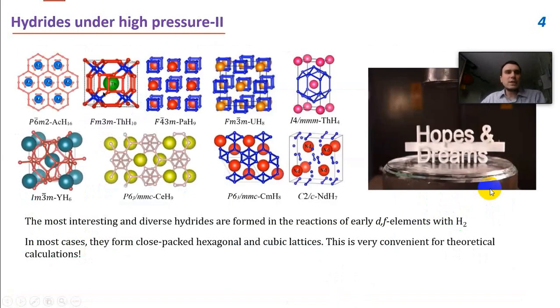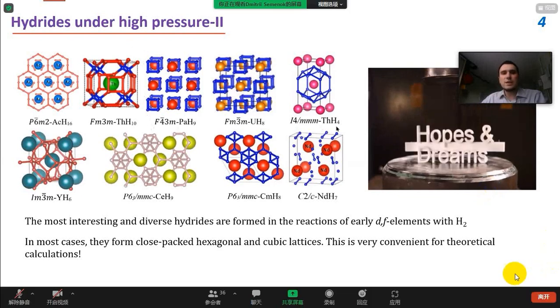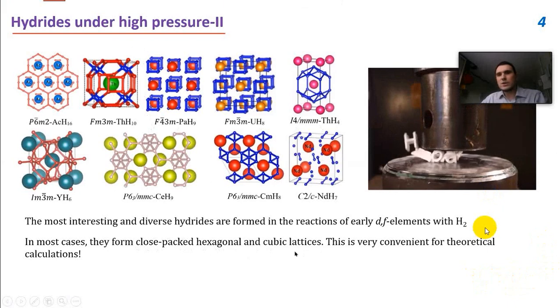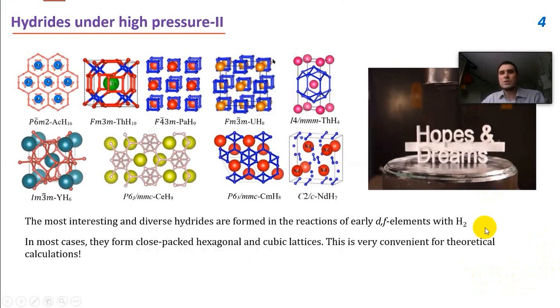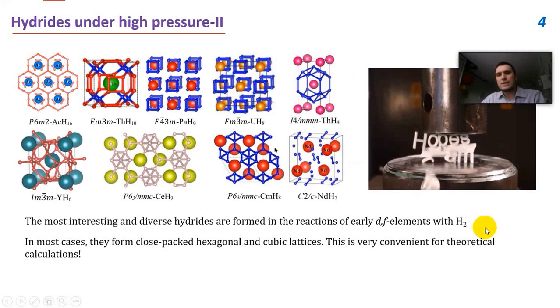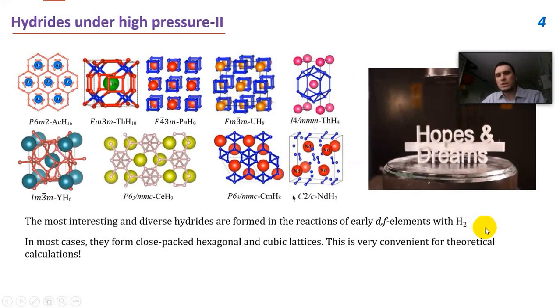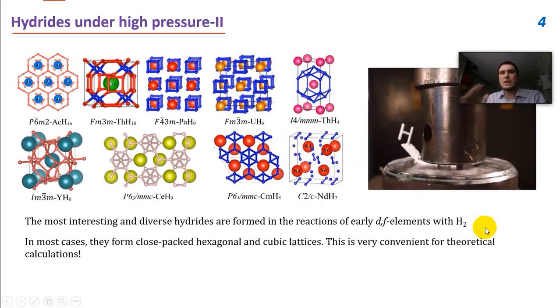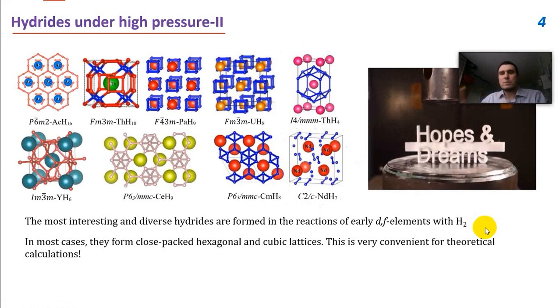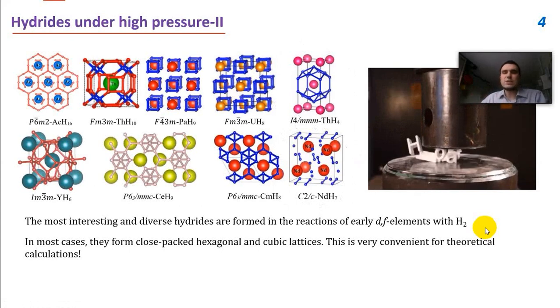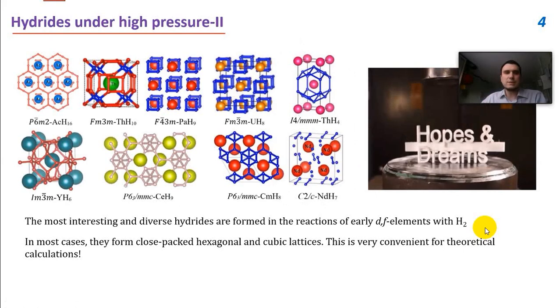Okay, I need to say that under pressure, a very important factor is volume, because these superhydrides prefer to crystallize in close-packed hexagonal and cubic lattices. So almost all superhydrides are cubic or hexagonal, and it is quite rare to find compounds with tetragonal lattice or with low symmetry lattice like neodymium H7. But typically they are close-packed structures, because under high pressure it's important to occupy positions with the maximum density. And atoms try to form crystals with maximum density.